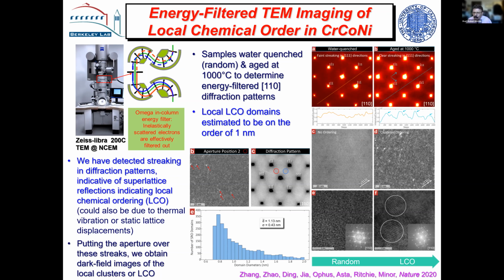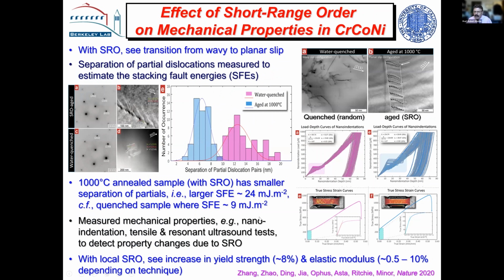But more interestingly is what effect it had. We see in the quench structure, which is supposed to be random, as opposed to the aged structure, which is supposed to have local ordering, you can see here, you get a change from wavy slip to planar slip. When we look at the spacing of the partials, which is an approximate way to get the stacking fault energy, in the material which has the random condition, then the spacing is larger, consistent with a small stacking fault energy. And in the case of the material which has the short range order in, then the spacing is smaller, consistent with a larger stacking fault energy.